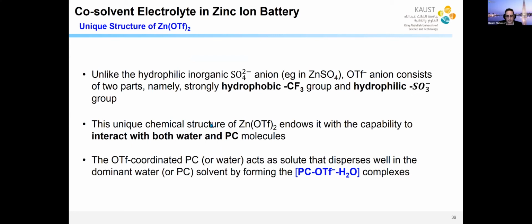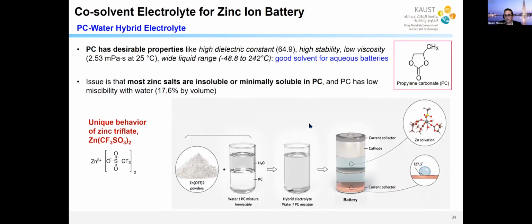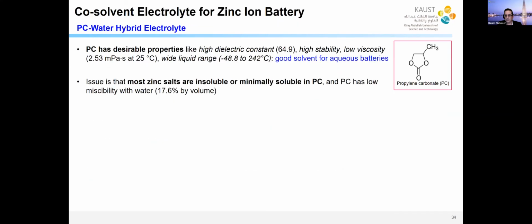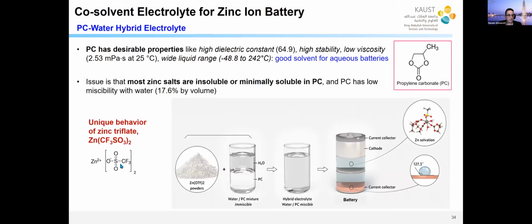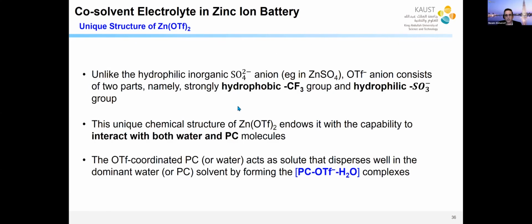We proposed one idea. Why is this happening with this triflate? What is different about this molecule, if you compare it to zinc sulfate, the most commonly used salt in batteries, is that in zinc sulfate the sulfate group is hydrophilic, but the OTF has two parts in its structure. If you look right here, you see there's this CF3 part and this oxygen part.